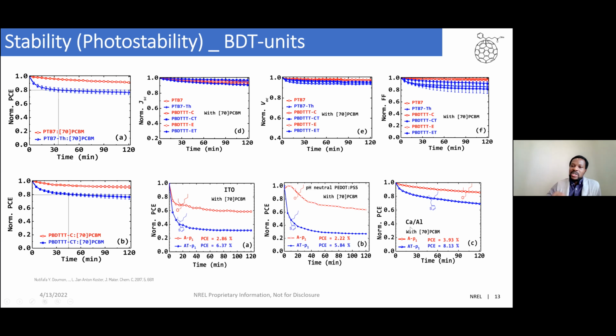And for the top contact, we also look at lithium fluoride, which we replace by calcium. And the trend still remains. So here we can strongly say that the differences we see in the performance of the red and the blue polymer are solely due to the change in that side chain.